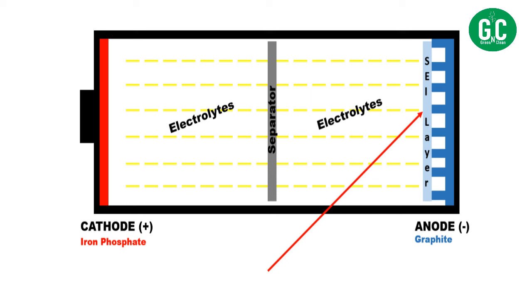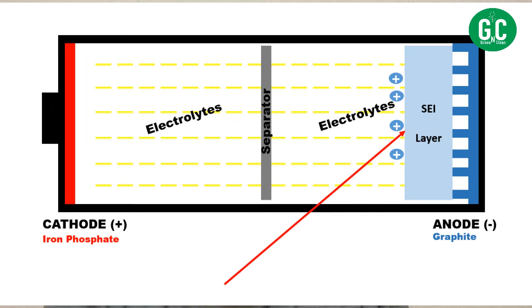So just to recap, the SEI layer which is formed at the anode is required to a certain extent, but frequent charging and discharging of batteries over a period of time causes this SEI layer to thicken, and when there is a thick layer of SEI, it acts as an inhibitor for lithium ions to move out of the anode, and that's reason number one why batteries degrade.